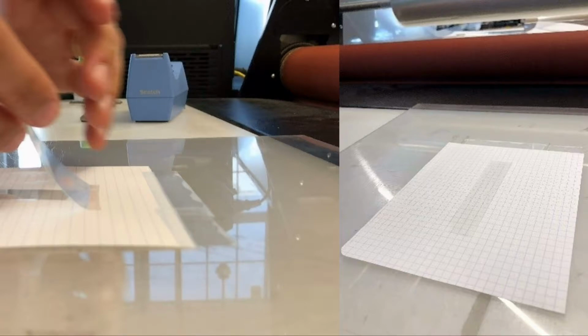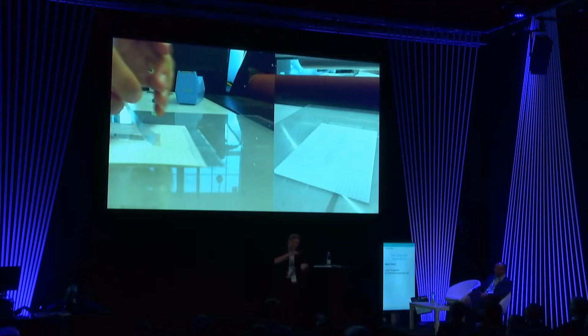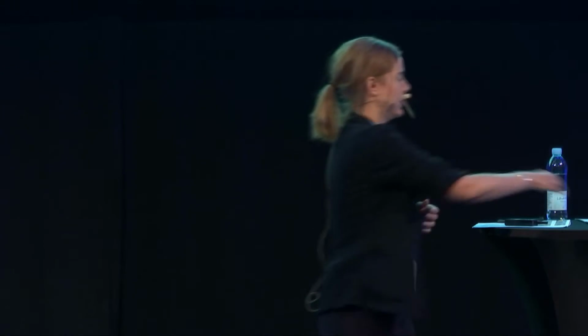Our neighbors were developing a product, a hologram product, which needed to be laminated, actually plastified like those library cards that you have. I don't know if you still have this anymore, but this kind of little cards. They used the exact same concept to plastify their hologram system. And that's actually at room temperature. You use a press. It's this very heavy steel press, not coated, but with a surface that's kind of rubbery. And basically how you do it is we wanted to do a laminate with 2 sheets of glass and an interlayer. It happened to be a PET film interlayer.